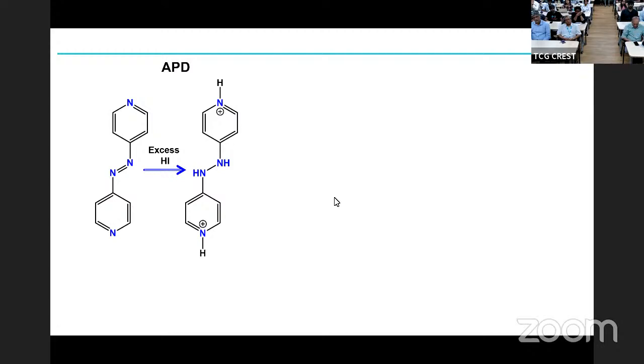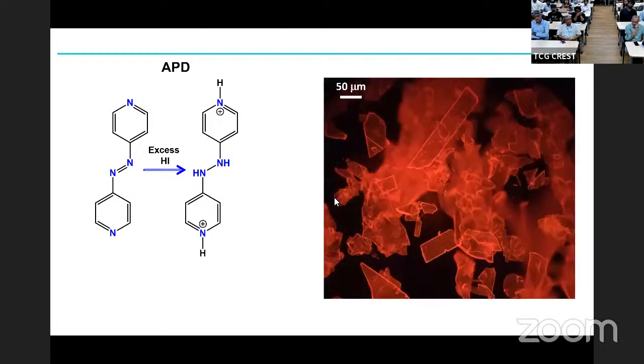It turned out that in preparing this, you do something to this head and that head, you protonate them such that this can now interact with the inorganic material. As I said, the head must have an affinity for the inorganic cage for you to be able to split open the inorganic layers. But this one, which we wanted to be delocalized, turned out to be also protonated, so it stopped being delocalized. But as I'll show you, it played a very important role in the properties that we get. This is just a picture of beautiful crystals that you can make from this material.